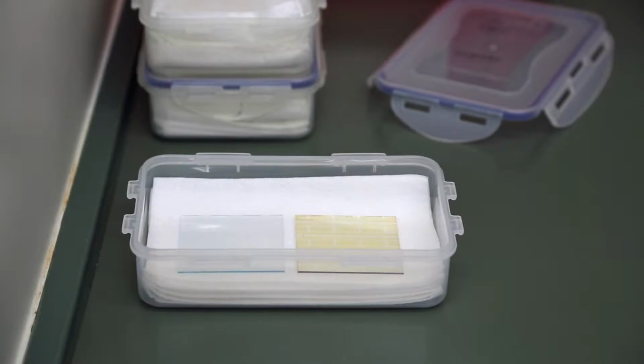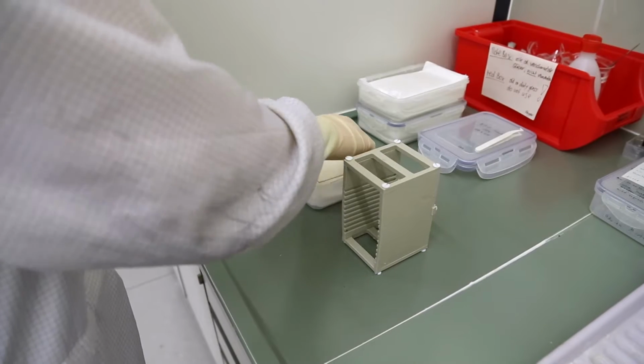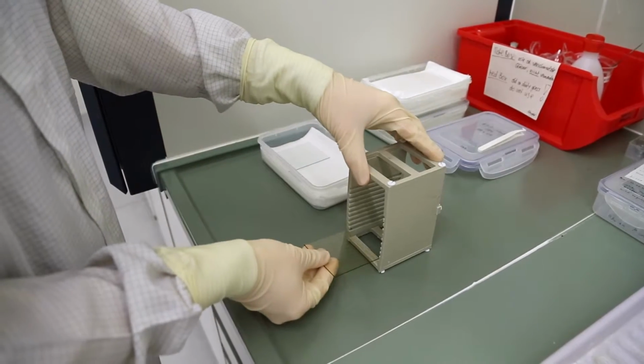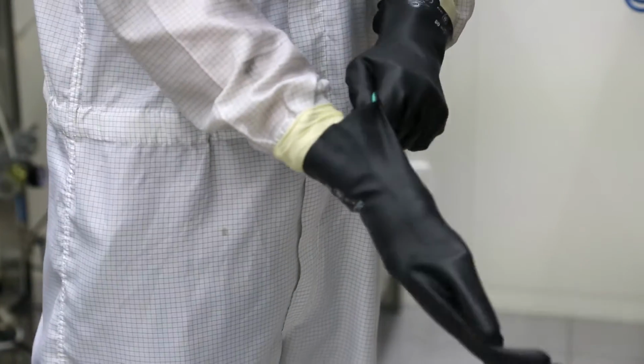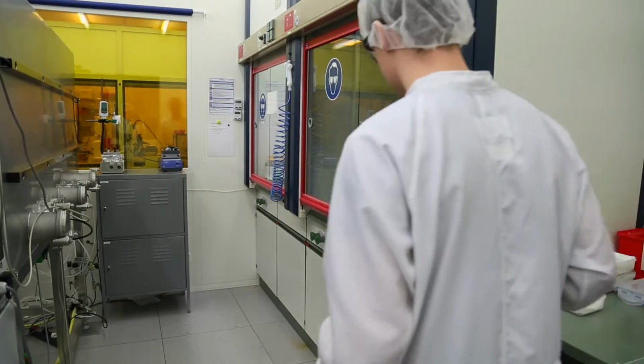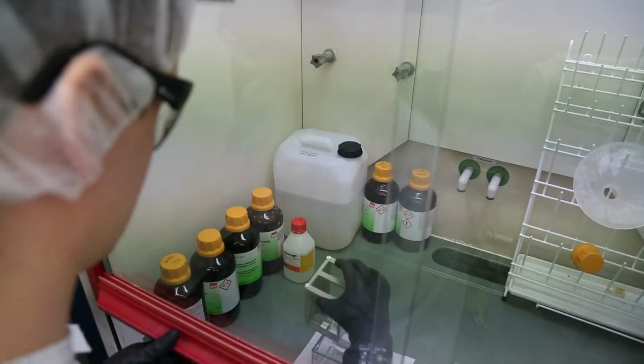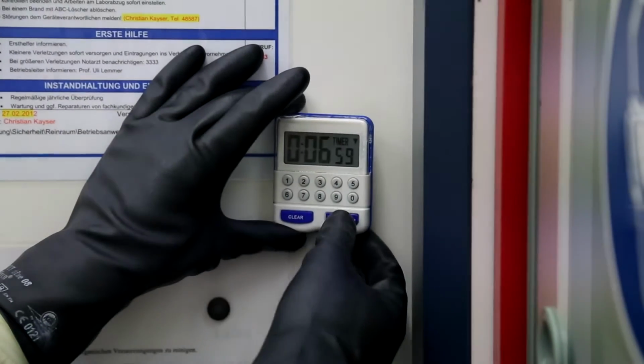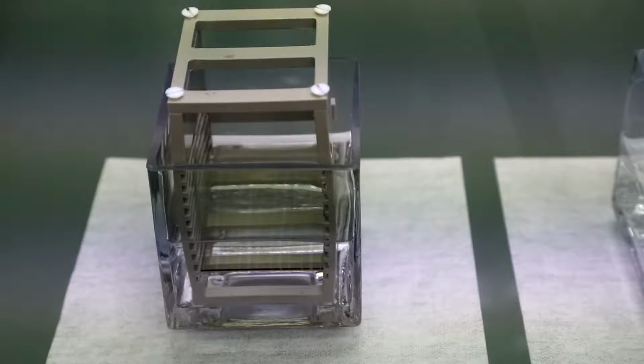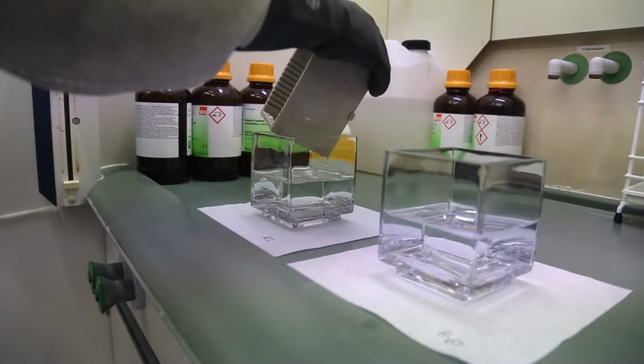The starting point is the anode, a coating consisting of indium tin oxide, abbreviated as ITO, deposited on a glass plate. The ITO is coated with a light-sensitive photoresist, which is developed only at the locations that are to be etched. The remaining parts will conduct the electricity later on, so the whole thing is similar to manufacturing a printed circuit board. In the first stage of the production process, Daniel Baru puts the exposed ITO layer into a container filled with half-concentrated hydrochloric acid. The acid etches away the exposed areas. Subsequently, the ITO layer is washed with distilled water.